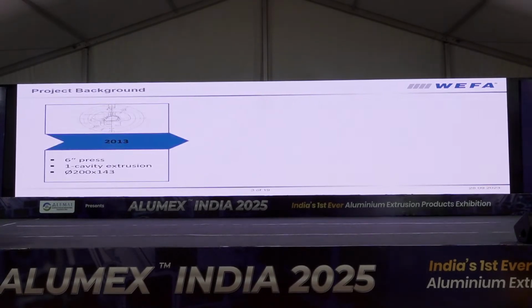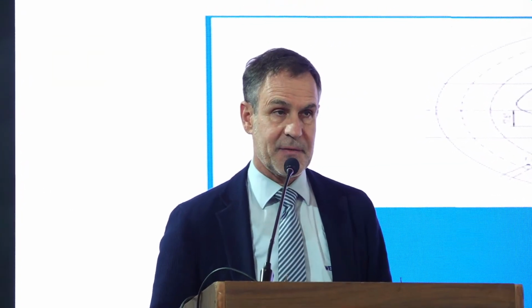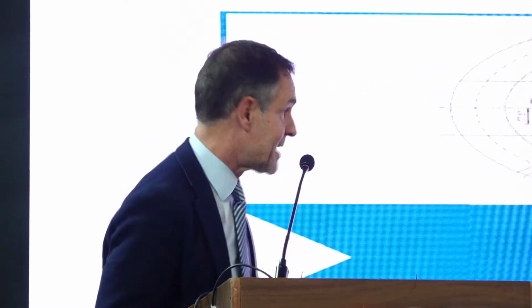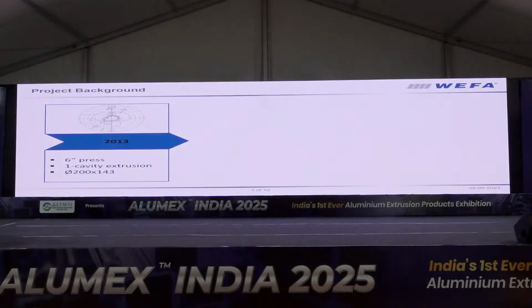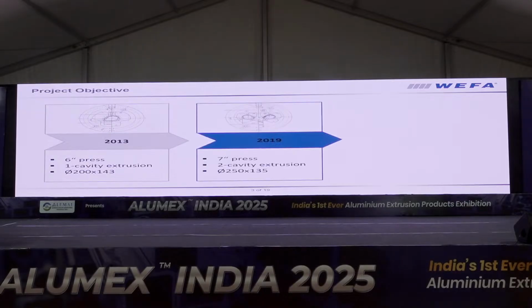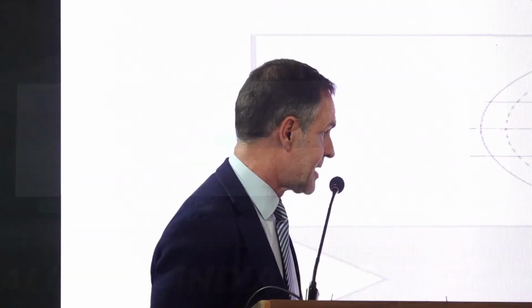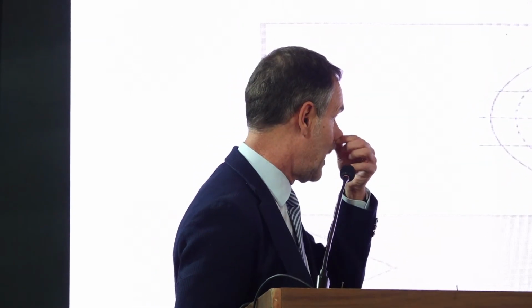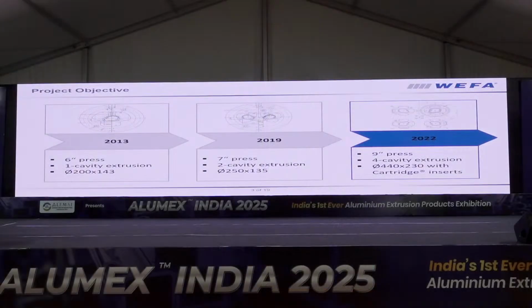So we had experience with a very old die from 2013. That was only a single cavity die on a 6-inch press, die size 200. In 2019, we tried to increase productivity. We increased the number of strands to two cavities and used a slightly bigger die. Then in 2022, we even tried to include a 4-cavity application in a much bigger die on a bigger press.